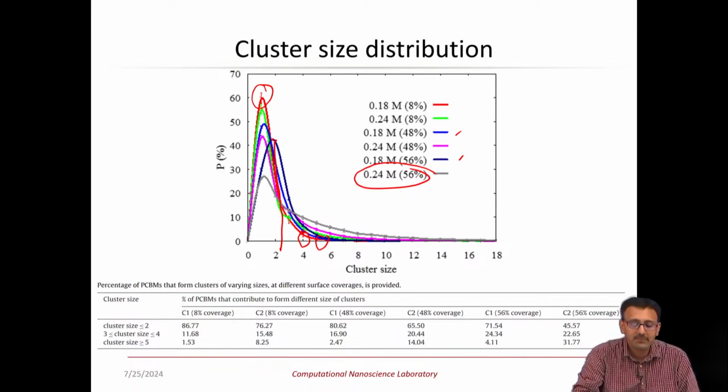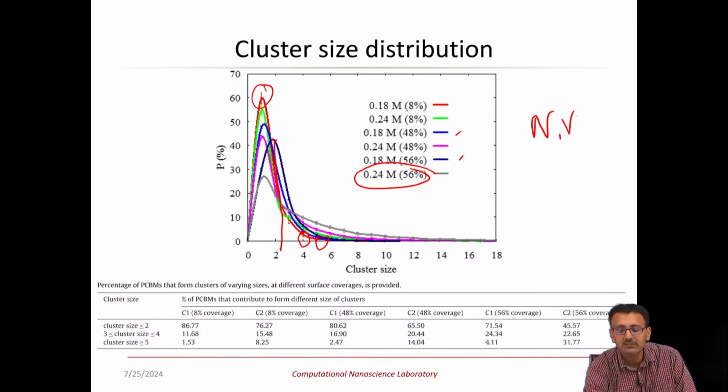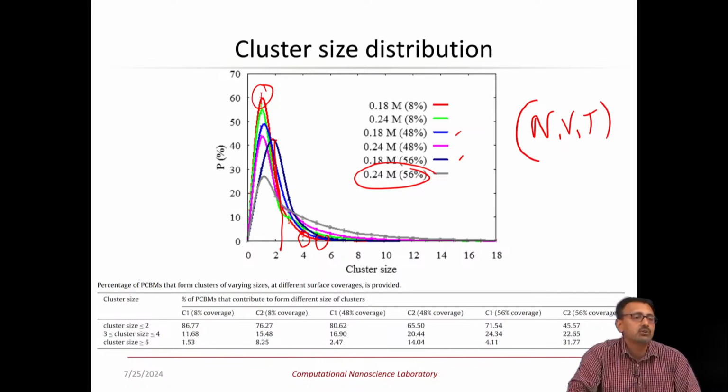If you do an NVT ensemble, a canonical ensemble is what you are modeling at the atomistic resolution. What is the challenge with this deposition process specifically? The challenge is you are depleting the number of molecules that are available to deposit on that surface as it happens, right. So, the driving force given by the concentration gradient, if you think of it from a continuum perspective, is getting lower and lower, right.